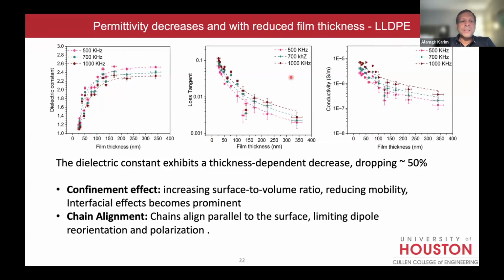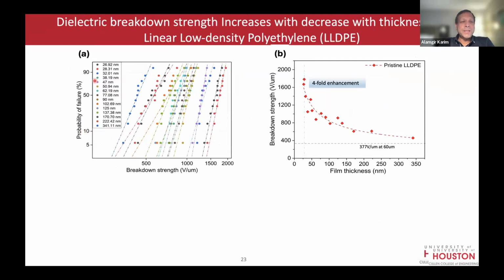Again, for LLDPE, linear low density, the dielectric constant, as I said, nothing you can do about it. It drops here, it drops in polypropylene, polyethylene, it drops below 150 nanometer. So this is not in our favor. This is actually how we measure breakdown strength. We increase the voltage. Any one of these is a different thickness. Okay, so you can see the thinnest one is this red one with a very steep curve. The way you measure this is called a Weibull plot. You increase the applied voltage at a given rate, like 25 volts per second, and it will go from low voltage to high voltage, and you measure the current that's going through the dielectric material. Anyway, the 63% value of this failure is reported as the breakdown strength.